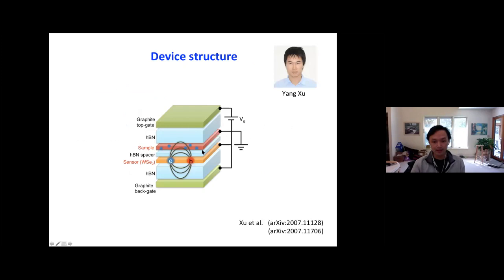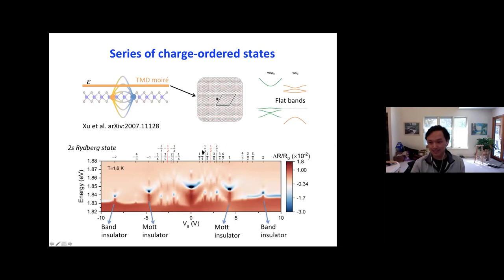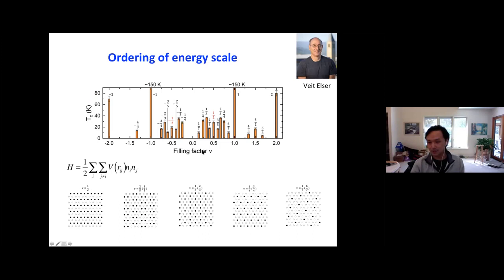And I don't really have time to go through how we detect this, but if you trust me, we have detected these states, and maybe I just immediately tell you what these states are. So our colleague Elser basically used an extended Hubbard model in the flat band limit. Basically, we just ignore the T. It's a purely classical model, and you can do Monte Carlo calculations to figure out what the ground state is at different commensurate filling factors.